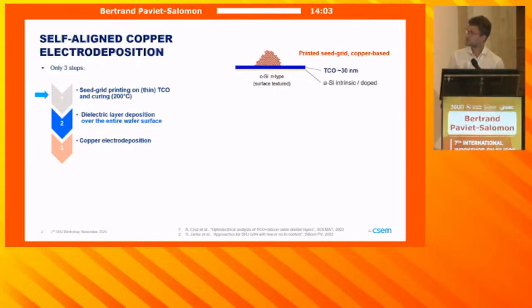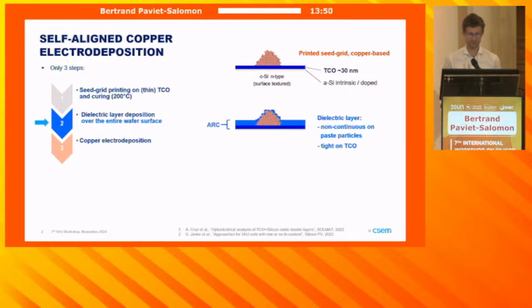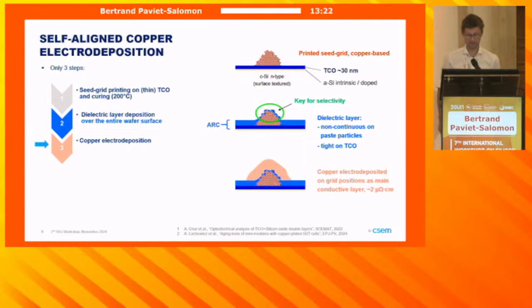It starts with screen printing a very shallow seed grid, ideally made out of pure copper materials, on top of heterojunction precursors with thin TCO. And then in the second step, which is actually kind of a key process, we deposit over the entire wafer surface a dielectric masking layer. This layer has 2 purposes. First of all, it aims at combining with the thin TCO to provide a good anti-reflection coating. And secondly, which is actually the key for the selectivity afterwards, is that this masking layer will stay very tight on the TCO, but will feature some discontinuities on top of the paste particles, and will leverage on these peculiarities to conduct, in the third step, the overplating of the seed grid only at those locations.